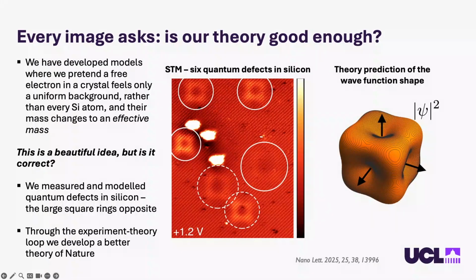And then what we've done is taken the silicon wafer to the University of Surrey, and we fired a high-energy beam of bismuth atoms. So we basically implanted bismuth atoms into this crystal, and the bismuth atoms are underneath the surface. So you can think about this bulk silicon crystal, and underneath the surface, every now and then, there's a bismuth atom.